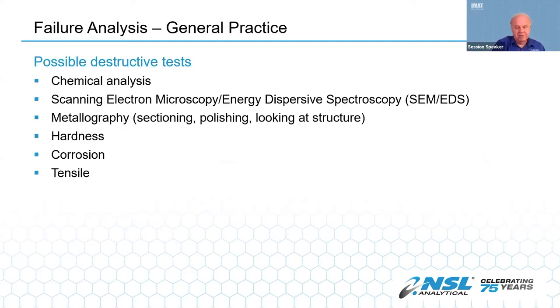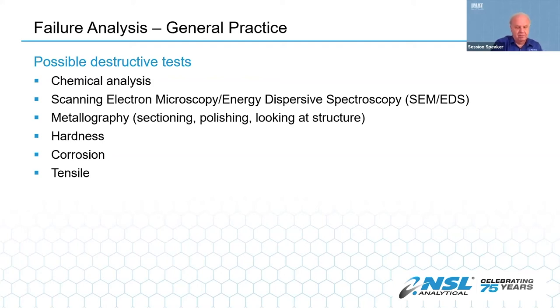I'll quickly go over some of the destructive tests that an analyst will do. The first four — chemical analysis, SEM-EDS, metallography, and hardness (either micro or macro) — are common tests that are performed, but there are many tests available. Corrosion and tensile tests are the most common, but they are dependent on the circumstances of the failure and how much material is available. Although many people would put the SEM under a non-destructive category, I put it in the usually destructive category, since most of the time you have to cut the piece up to examine it.